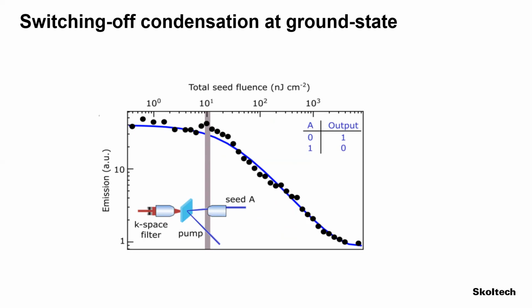So let's look now at the emission spectrum. If I have a seed fluence for the control beam which is very small, you look here at the emission from the condensate. And as I increase the seed fluence of the control beam that comes at the non-ground state, the emission of the condensate is switching off. And clearly here it's switching off over orders of magnitude. So a small control beam can switch off the emission from the condensate by more than an order of magnitude. Well, that is the NOT gate. The NOT gate, the inverted gate, is instrumental for full logic.